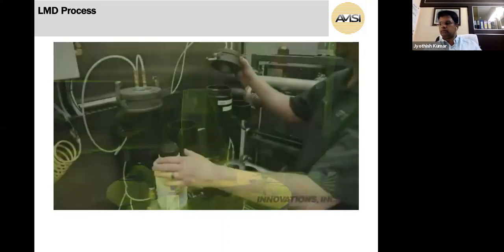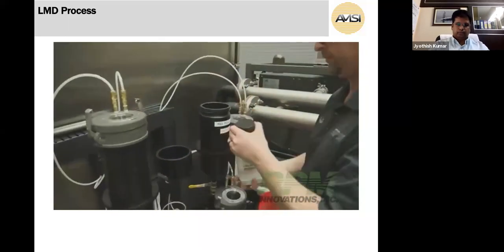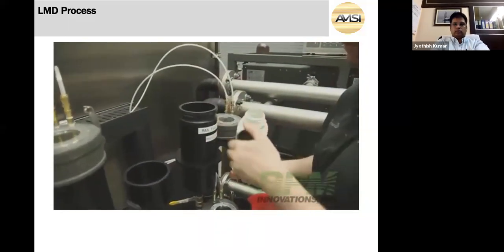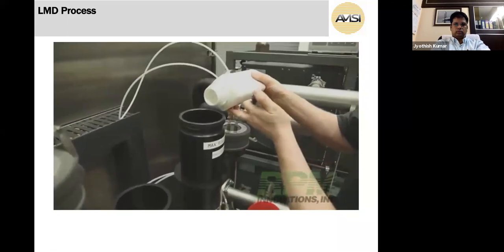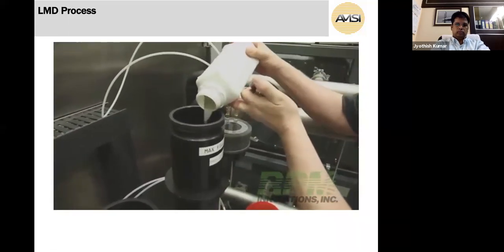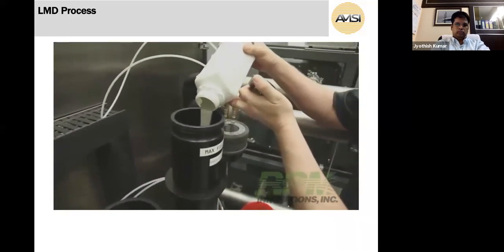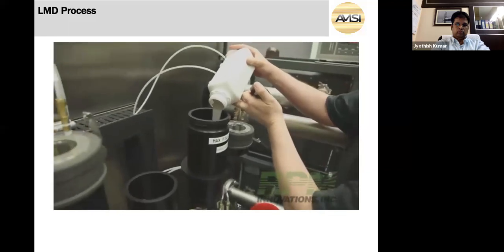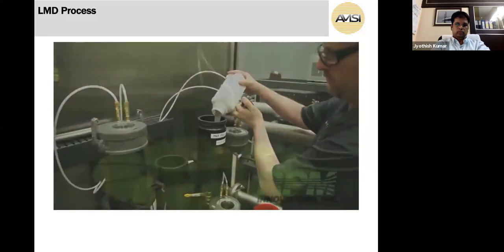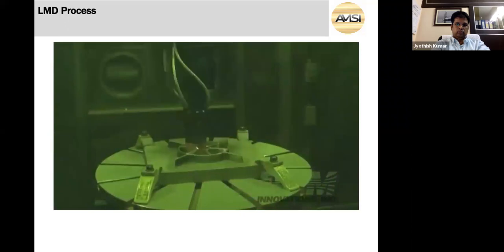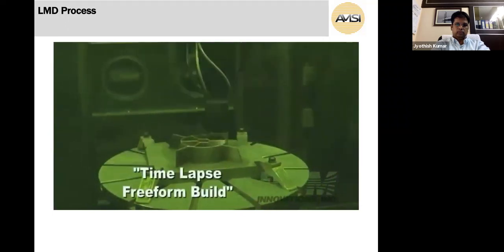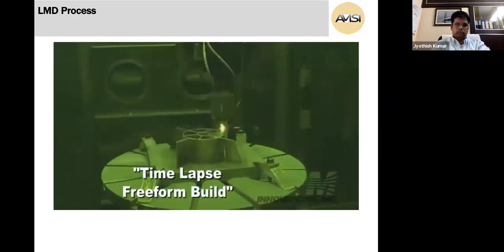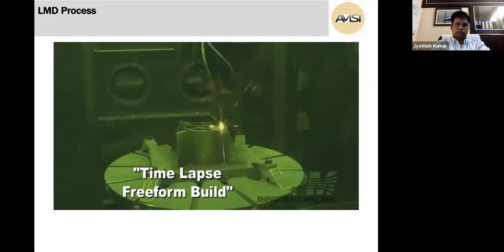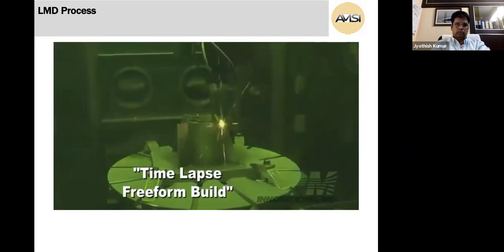A variety of alloys can be used in this process, including tool steels, stainless steels, nickel, cobalt, and titanium alloys. Deposit quality and consistency is of primary importance for all laser deposits. Weld beads are produced in a very low oxygen environment with a very small laser spot size and relatively high travel speeds. The laser deposits have extremely high cooling rates.